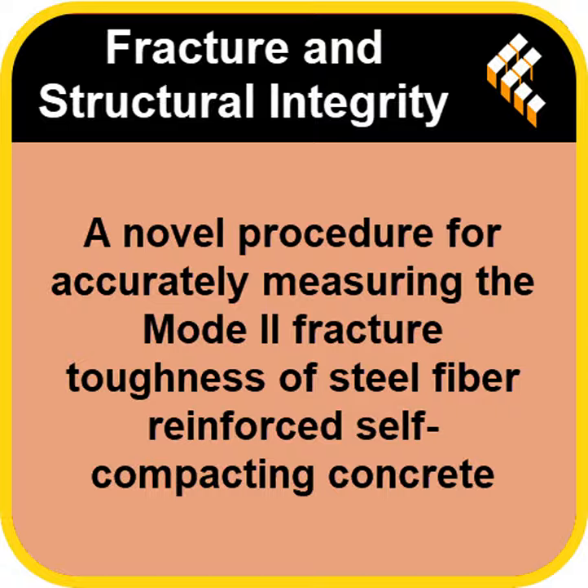And finally, the realistic one. Series 4, MEC, the matrix crack specimen. Fibers uniformly distributed everywhere, including across that carefully created crack surface. This represents the actual material in a structure.